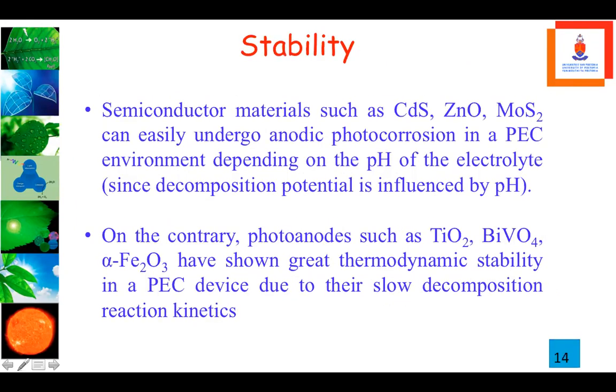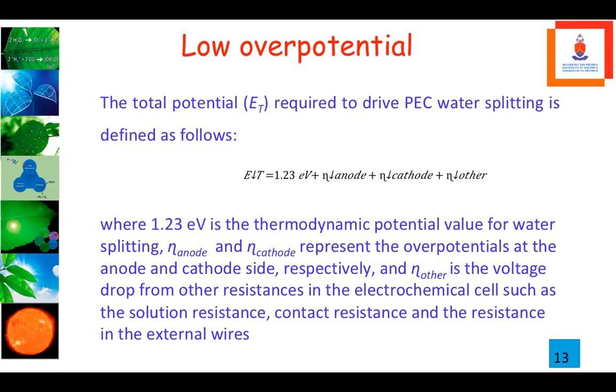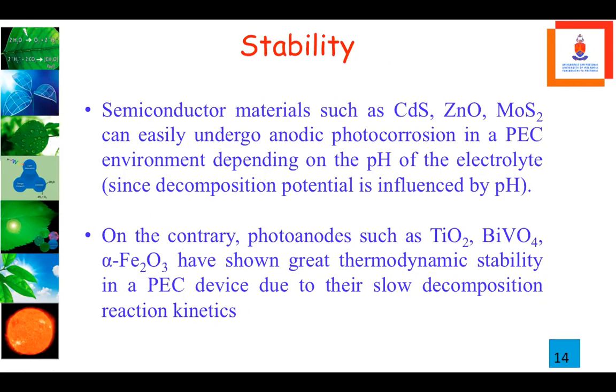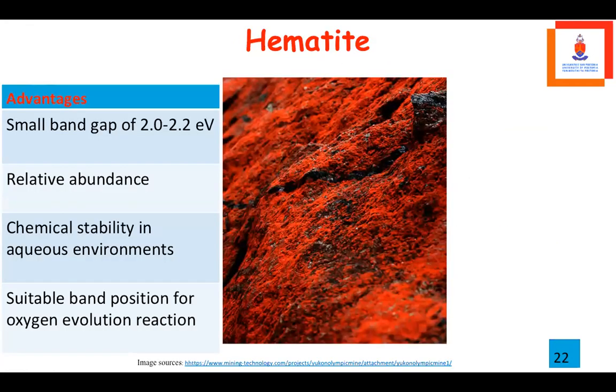And with all of this, we are looking at hematite as a stable material inside water, which can be used to make a device called a photoelectrochemical cell so that we can split water into hydrogen and oxygen. And in that work of splitting water into hydrogen and oxygen using hematite, we are struggling with some issues. The advantage of hematite is that it has this band gap, which can capture up to 40% of the solar energy.